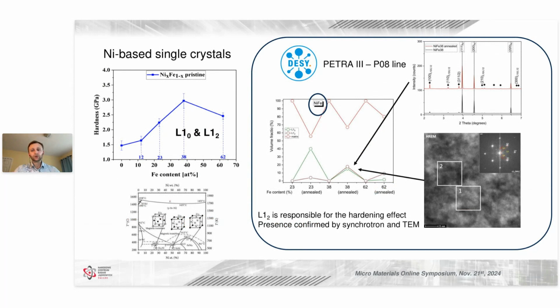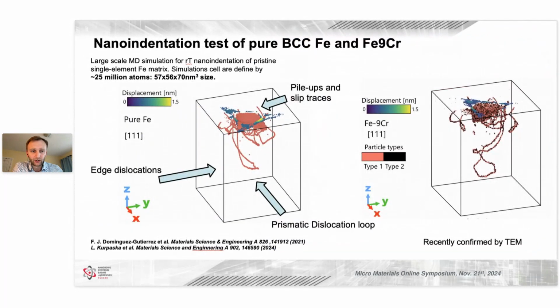So what's going on? Again, we went into deeper structural studies by using synchrotron and high-resolution TEM, and we saw that the FCC lattice, because of the temperature, reorganizes itself and creates L12 or L10 phases, which limit dislocation motions. And these local reorganized structures are responsible for the recorded hardening effect. As I said, numerical modeling is quite handy, and we recently proved that there is a migration of chromium atoms in the proximity of dislocations developed due to nanoindentation, and those chromium atoms limit motion of the dislocations, which is causing the hardening. This is one step to understand better the behavior of Eurofer 97 in the nuclear environment.